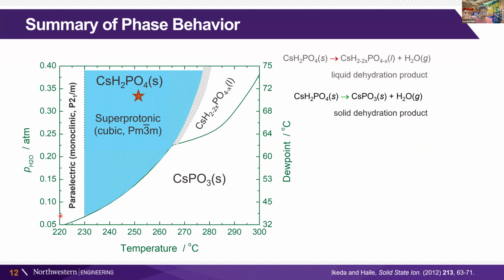We put all of the results together, and we see that there's this window in which the superprotonic phase is stable. The transition temperature to that cubic phase is around 228 to 230 degrees Celsius. That's about our uncertainty in that number. And we have two dehydration reactions. One at low steam partial pressure goes directly to the metaphosphate. And at higher partial pressures, the transition is through a liquid phase first, which is then followed by a transition to the solid dehydration product.